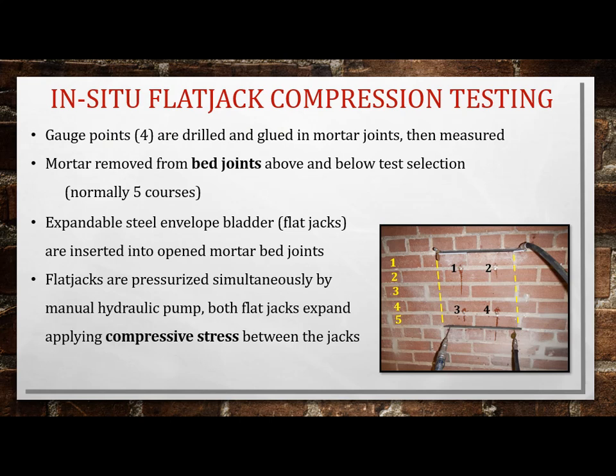And then you take a circular saw, and you cut out the mortar joint above it, mortar joint below it, and you slip this hydraulic jack inside the mortar joint, and it's a tight fit. So then when you start pumping your jack, it expands, and so it's actually inducing a force up and down, but since you got 2 of them scissored together, you're actually squeezing, implying a compressive stress between the jacks.